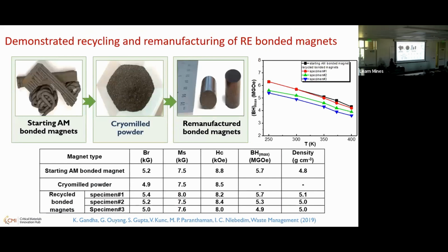Here, if you take the magnets, simple, you crush the polymer, because polymers crumble into powder. The whole idea, I forgot to tell you, compared to cold spray or metal additive, the reason we went into a polymer bonded magnet is we are relying only on the polymer melting. So the magnet is still maintained, and there is no degradation when you go through this process. So you can really do it.